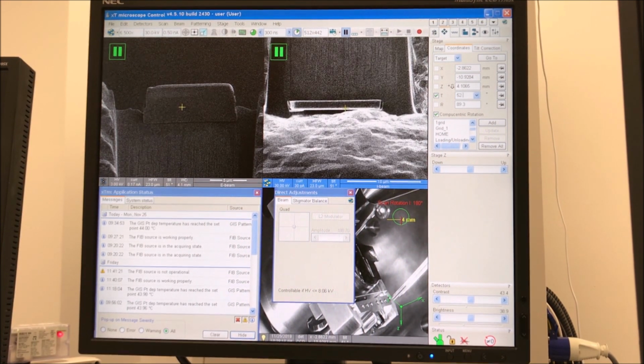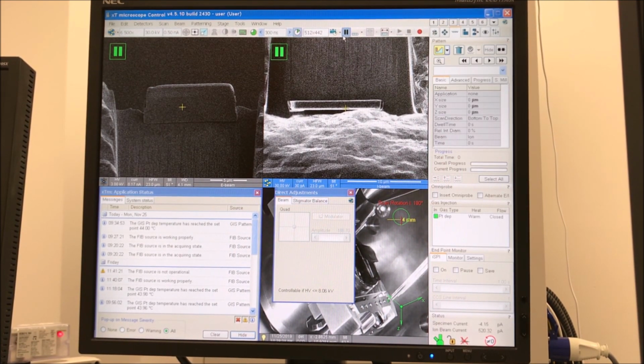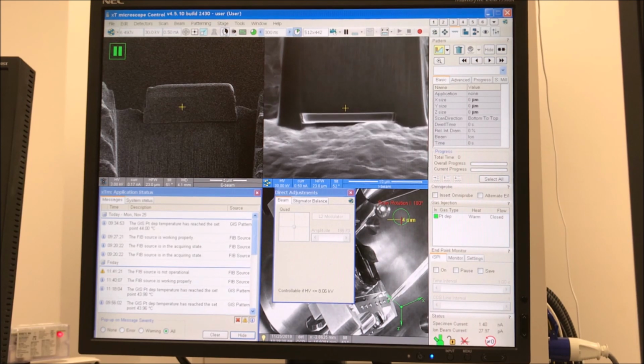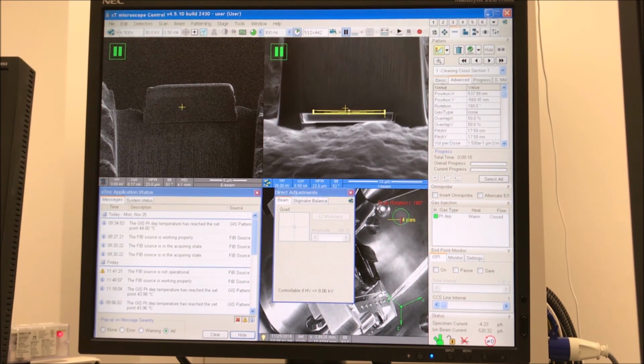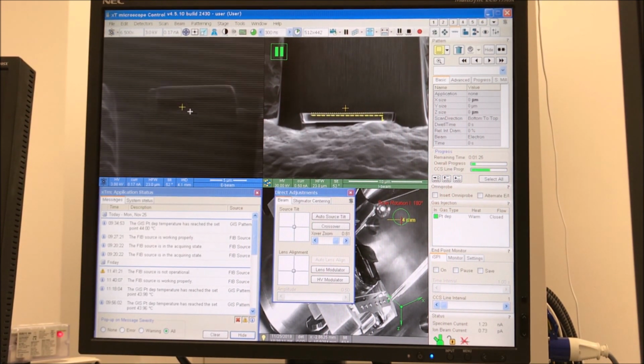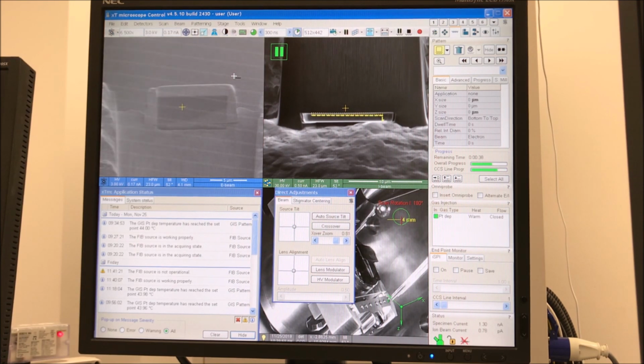Now I'm going to go up to 0.5 nanoamps. I'm going to tilt plus 1 degree from normal incidence, and I'm going to now use a cleaning cross section on the upper side of the lamella. And so you want to make this a couple hundred nanometers in the Y dimension. With the X, I'm starting with 10 microns, and the Z is about 2. And so this is going to be most of the final thinning with the cleaning cross-section pattern. And we can actually see that side of the lamella being thinned in the electron beam image.